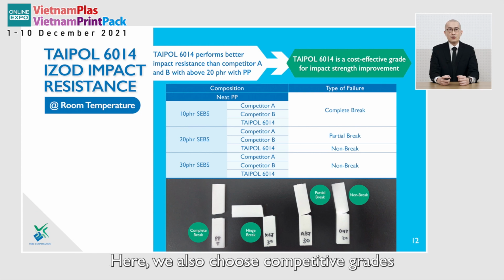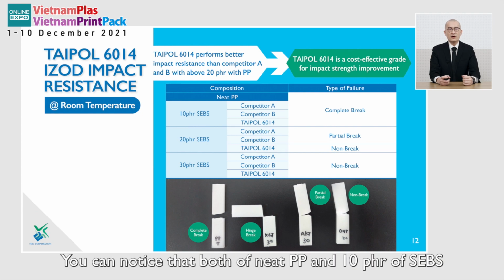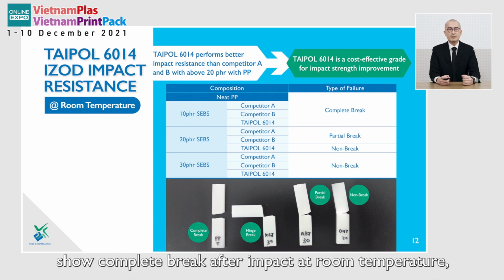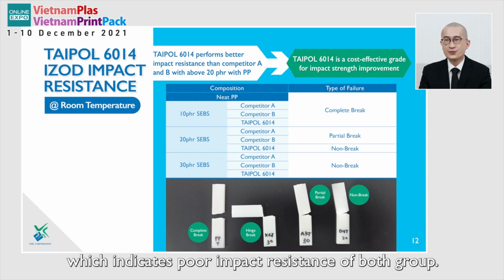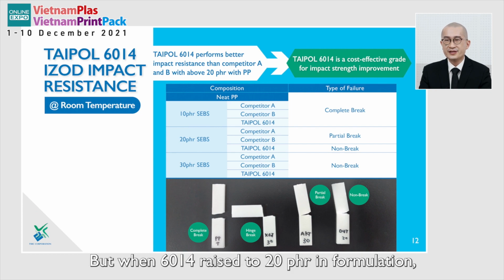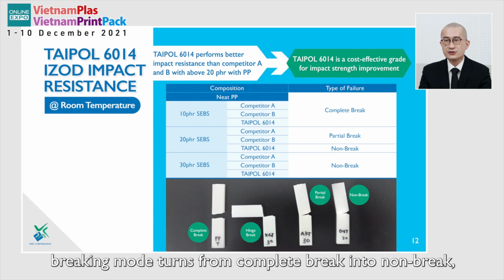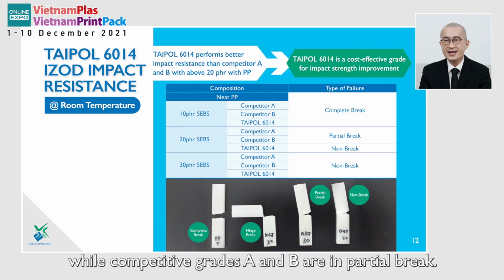Here, we will also choose competitive grades A and B for comparison. You can notice that both the neat polymer and 10 phr of SEBS show complete break after impact at room temperature, which indicates poor impact resistance of both groups. But when 6014 is raised to 20 phr in formulations, the breaking mode turns from complete break into non-break, while competitive grades A and B are in partial break.